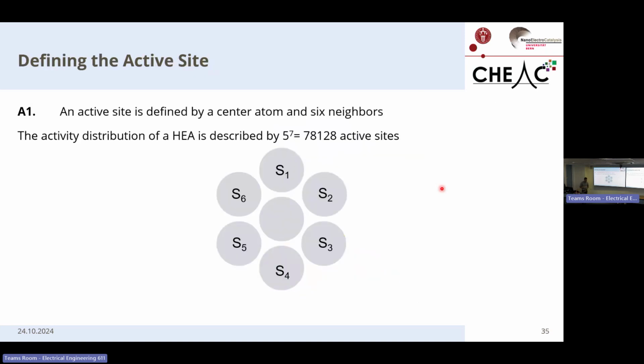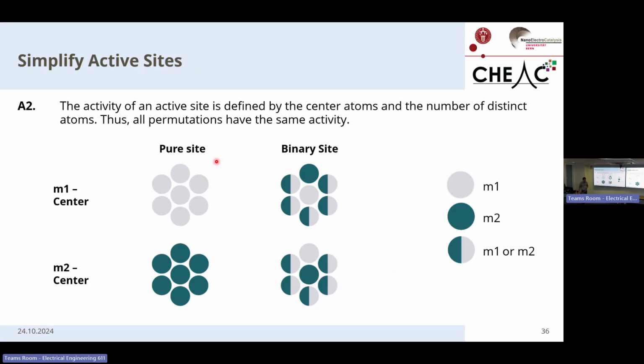So let's derive this statistical model together. The very first thing we need to do if we are making a model is to get our definitions straight. So in this case, I decided to define an active site as this 7-atom arrangement, 1 center atom, 6 atoms in the surrounding. So if we now have a 5-element alloy, we end up with 78128 possible different active sites. I don't think people like to work with such a large amount, so let's simplify it.